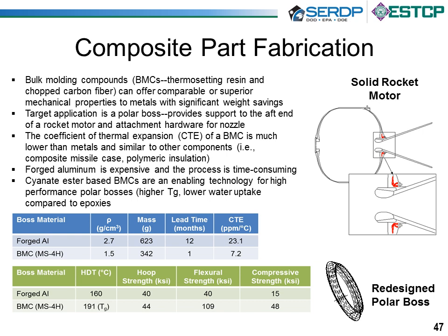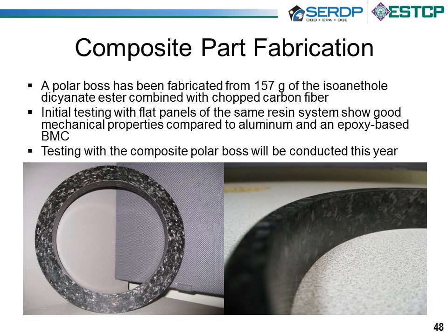So let's move on to see a picture of a polar boss that we actually made. So you can see two views of a polar boss that was prepared. This was done by the Air Force Research Laboratory. So this is composed of 157 grams of the isoanethole dicyanate ester that we looked at earlier. The reason we used that resin was the fact that it's a liquid at room temperature. We've done initial testing with flat panels of this resin system, and they compare very well to both aluminum and epoxy-based bulk molding compounds. And we're constructing a specialized test stand to actually perform physical testing on these polar bosses this year, so that testing will be complete this year.